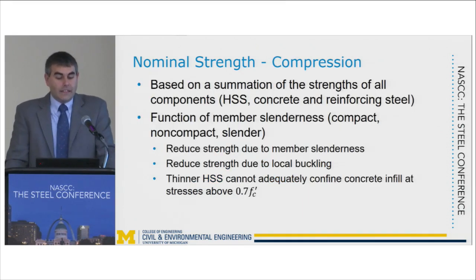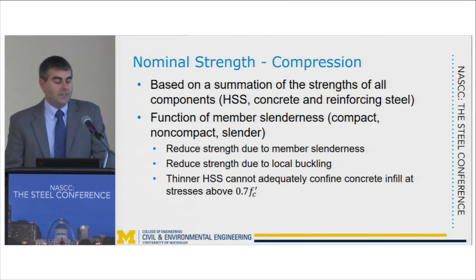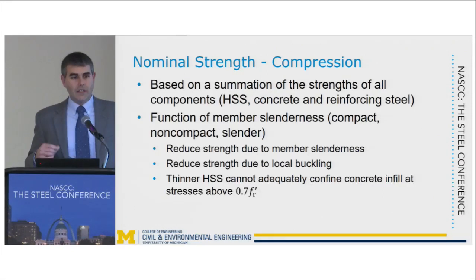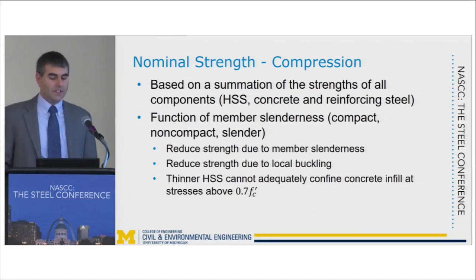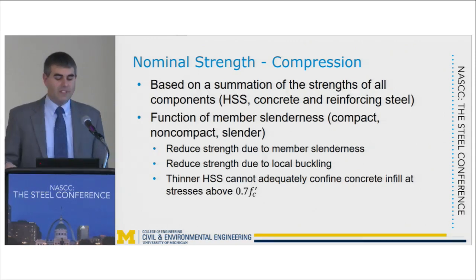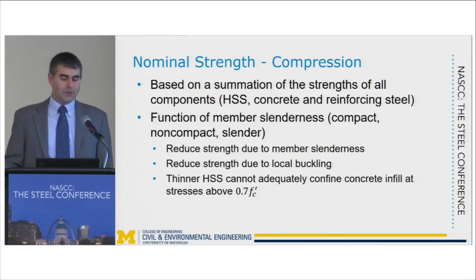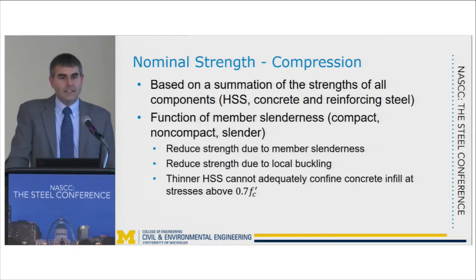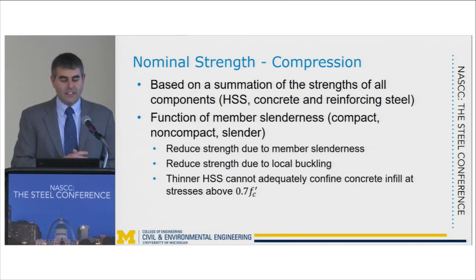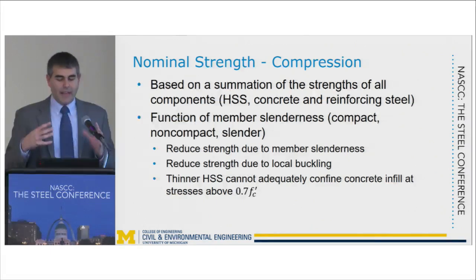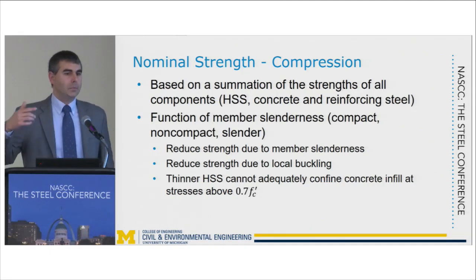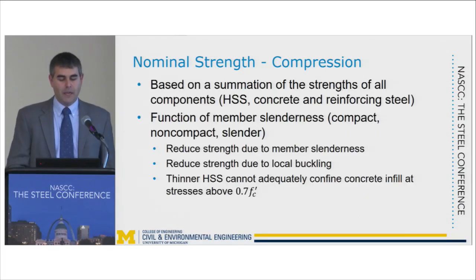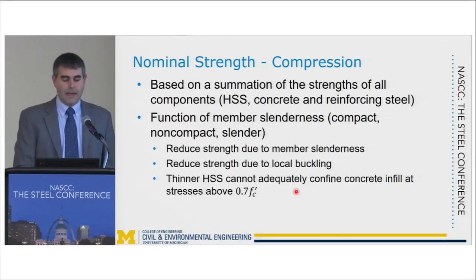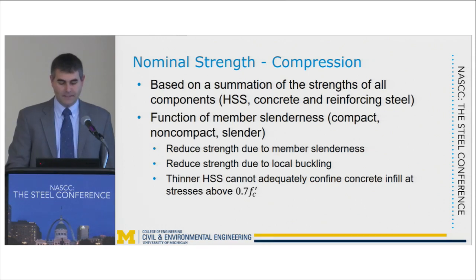Now, if we look at nominal strength in compression, this is based on the summation of the strengths of all the components, the HSS, the concrete, and the reinforcing steel. And again, it's a function of the member slenderness. So the first thing that you need to figure out is whether you have a compact, non-compact, or slender section, so you can reduce the strength based on the member slenderness and account for a reduced strength due to local buckling. Now, the other thing to keep in mind is that if you're dealing with a thinner hollow structural section here, the walls are too thin to adequately confine the concrete to allow it to get up to 0.85 f'c or 0.95 f'c. So you reduce the maximum stress to 0.7 f'c.